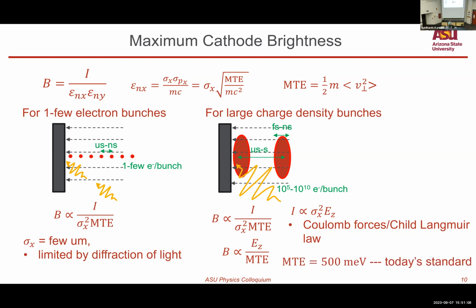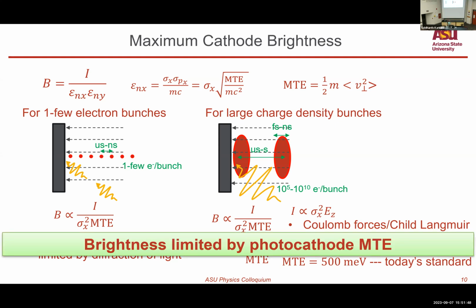Now, to set a scale, in most applications today, the mean transverse energy is a few hundred millielectron volts. And often when people design an accelerator, they assume that the mean transverse energy is going to be 500 millielectron volts. It's sort of a safe assumption. In most cases, people pick a convenient laser that they have. They use the most convenient surface to emit electrons from, which is usually the back plate of their electron gun, and they get whatever MTE they get, and it's treated as a magical number that they obtain. And they usually assume it's 500 millielectron volts. And that's something we are trying to change. And we have done so quite a bit.